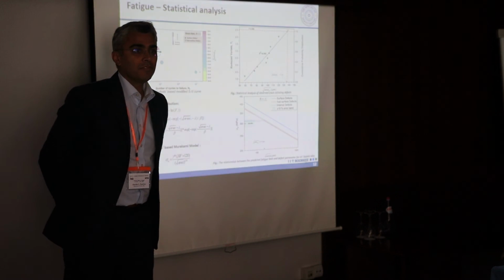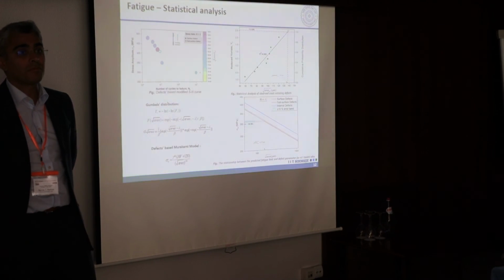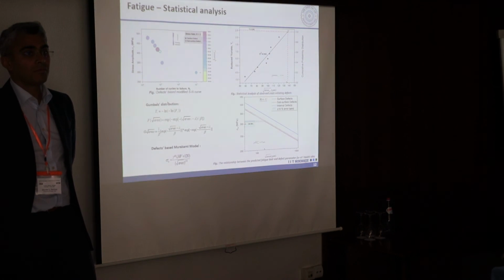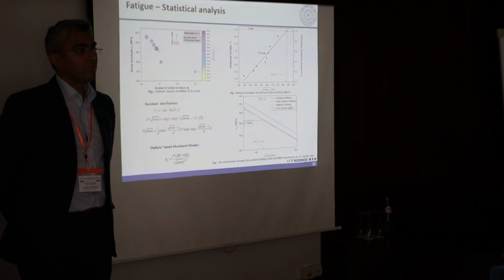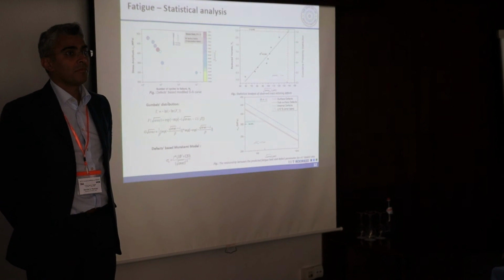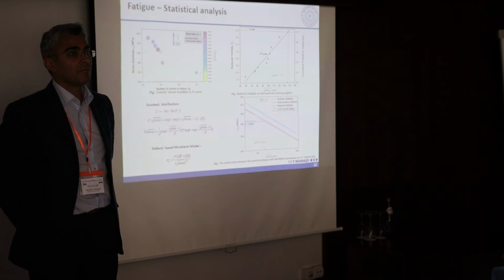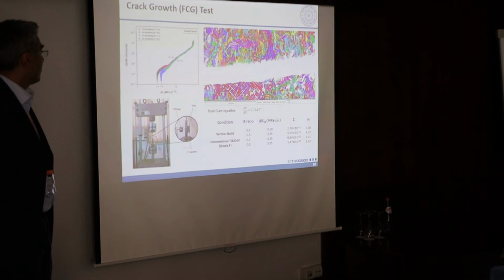Any other questions? As we know, when we fabricate titanium, we have different directions, the scanning speed directions or the longitudinal directions. Which direction do you mark on the video? Vertical. Okay, I'm just curious about the result of your EBSD. Did you detect the grain size? No, we have not evaluated the grain size. In that case, we evaluated the alpha lath thickness.